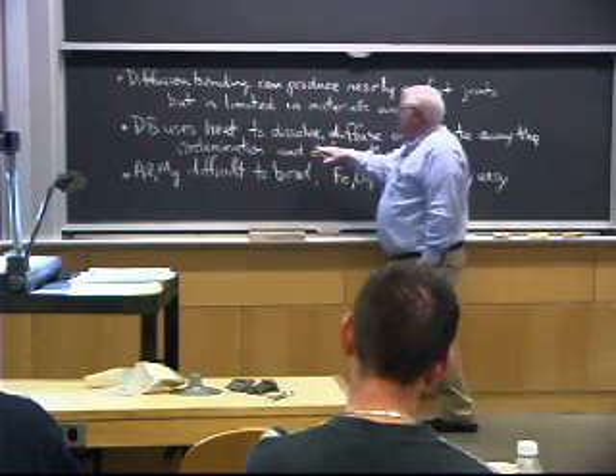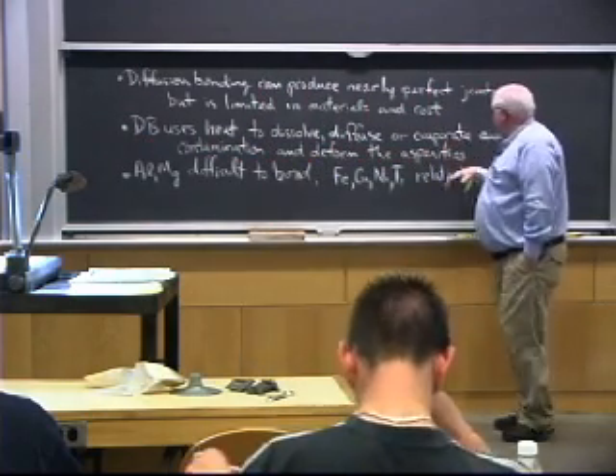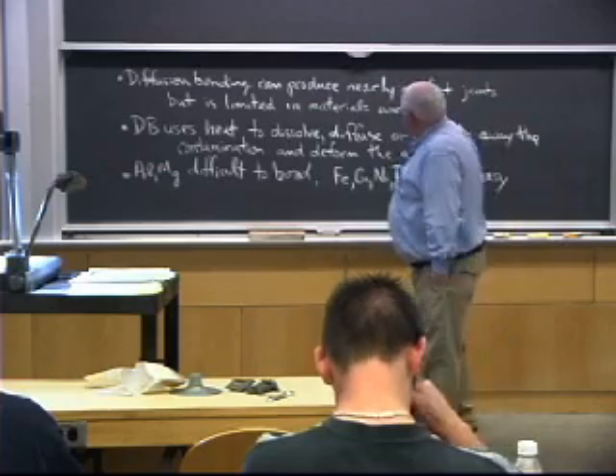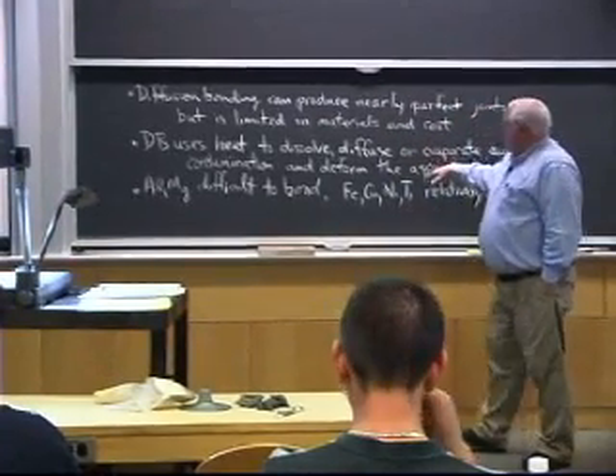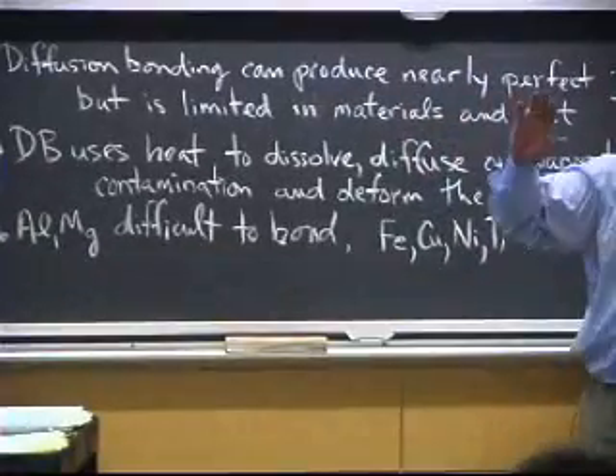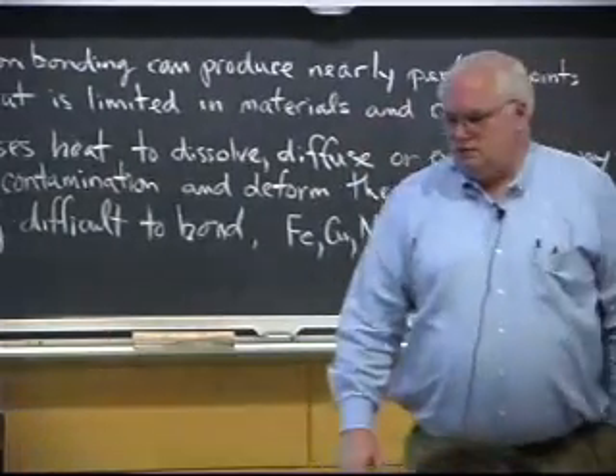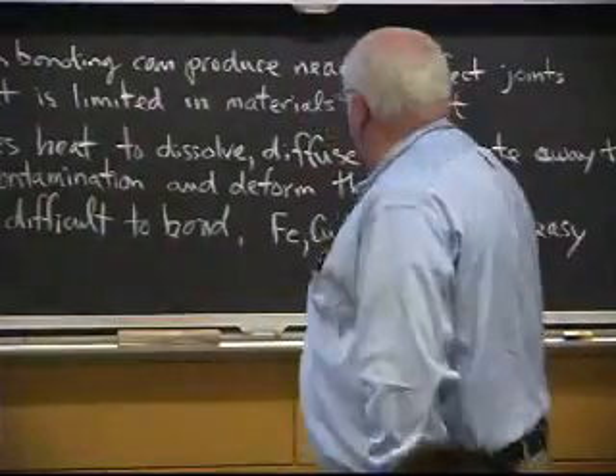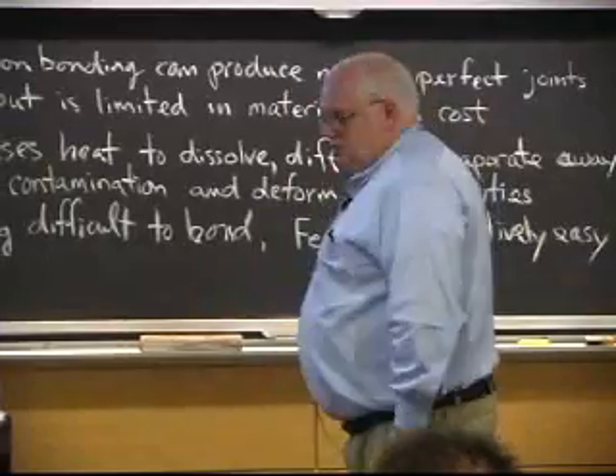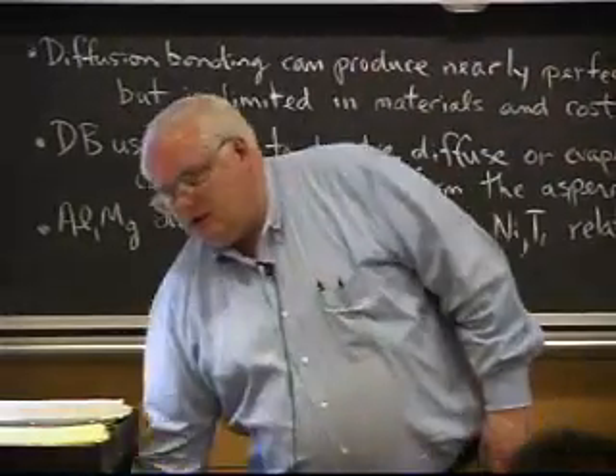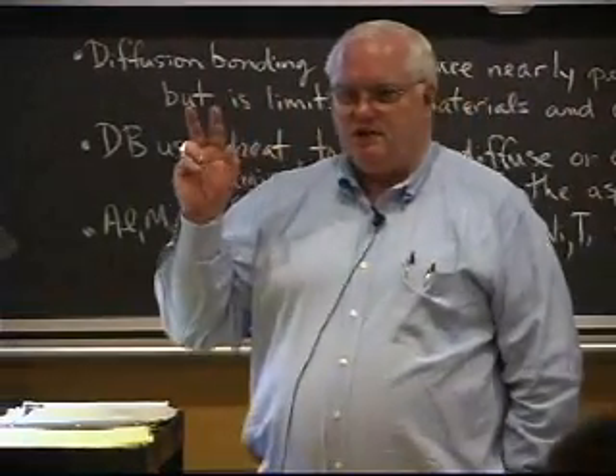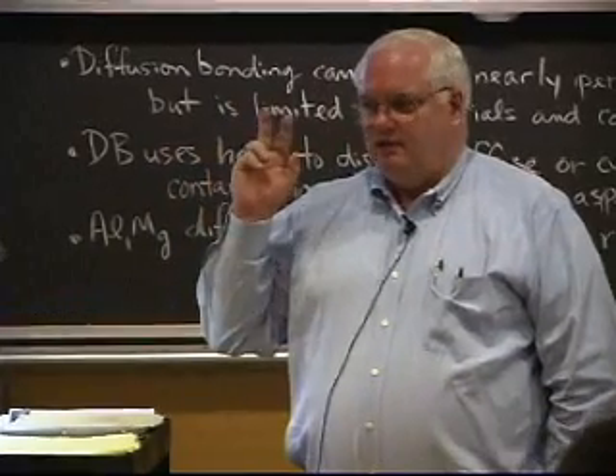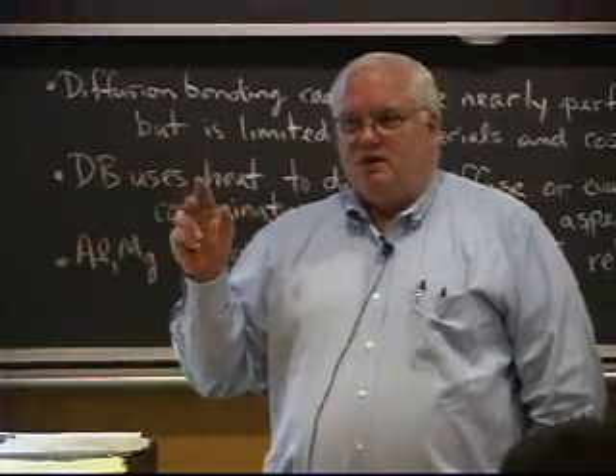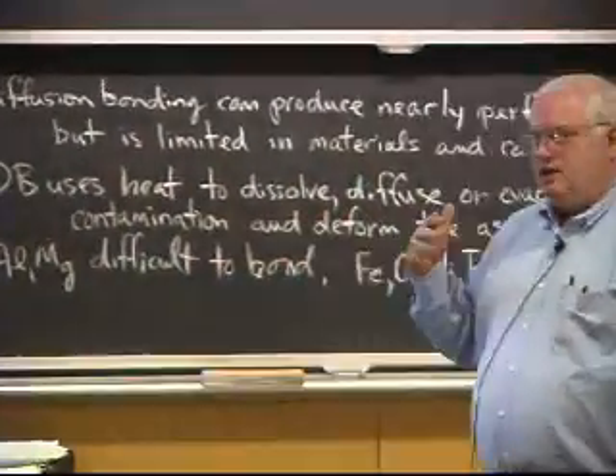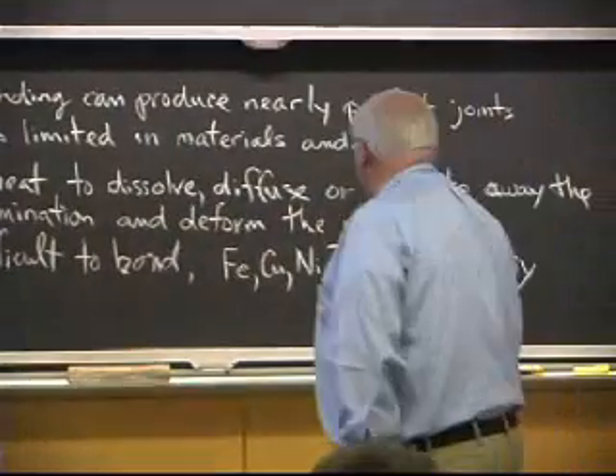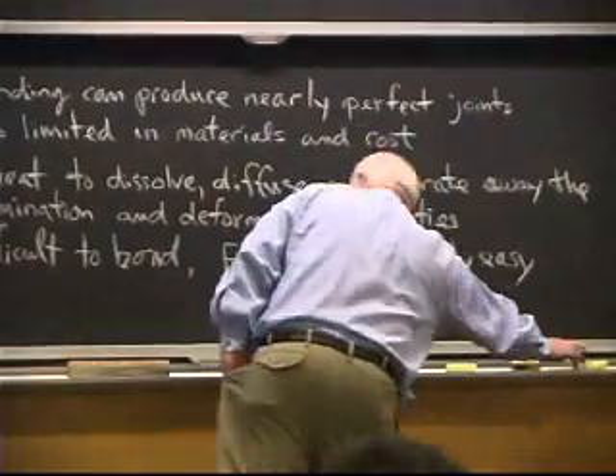Diffusion bonding uses heat to dissolve, diffuse, or evaporate away the contamination. It evaporates away the moisture in the oils, and it diffuses and dissolves the oxides or sulfides or whatever else is on that surface, carbon sometimes. And it uses heat to deform the asperities. So going back to this theme of you got two problems to bonding things together: surface contact area and contamination. And the way diffusion bonding solves it is just adding heat and pressure.